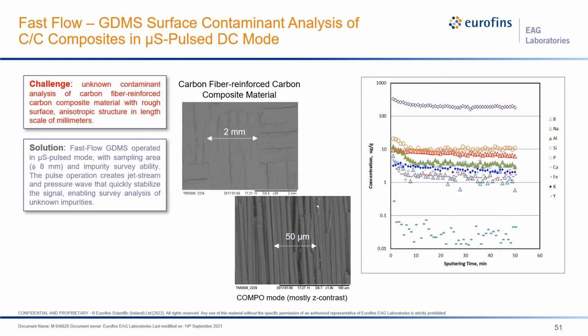The third example, or the last example we are trying to show here, is ceramic matrix composite materials. You can see it has very rough surface features. The length scale of anisotropy is a few microns to a few millimeters. And here shows detailed structures at the 50 micron scale, and you can see it's very rough. So how do you do the surface contaminant analysis of this one? You don't know the contaminant level, you don't know what kind of contaminants, and it's a very rough surface, and it has a very anisotropic structure in length scales of millimeters.